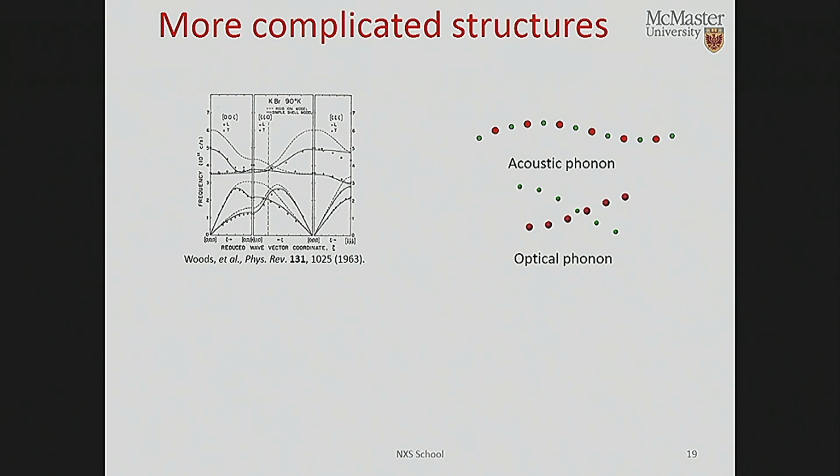Okay? And in particular, the same thing can happen. Having more than one atom per unit cell, you can get the same sort of longitudinal phonons and transverse phonons that we had before. In that case, it just means that if you've got two different types of atoms, a heavy red atom and a light green atom, they basically oscillate together in phase. And the motion here is really the motion of an entire unit cell together. So an entire unit cell is moving in one direction, and then it moves back in the other direction. Okay, and so that's what you see here for these acoustic phonons.